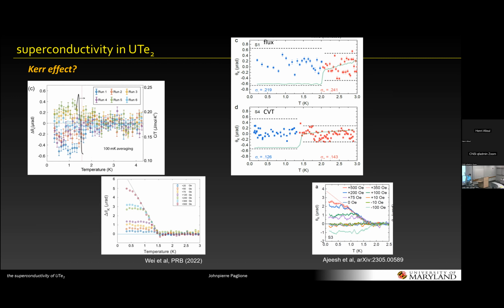Los Alamos has claimed that when they do that, at zero field, and they use a different technique, they don't see any envelope. In fact, these dashed lines here are the envelope from Aaron's experiment, so they claim that they don't see any difference. But this residual field is always very tricky. Yeah, and there's a domain question here too. Los Alamos will be different from California.